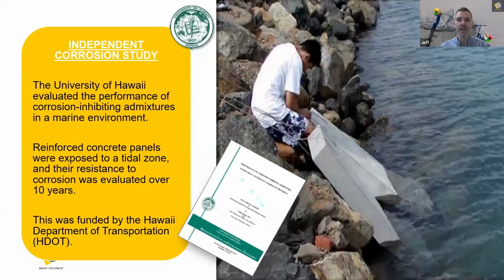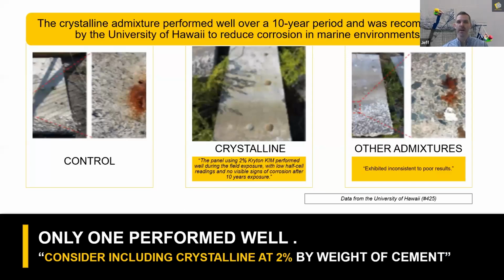Now, a really interesting study on this topic was performed by the University of Hawaii. This was a completely independent study where they exposed reinforced concrete panels in the harbor zone for 10 years. So what we're getting now is all of the critical corrosion-inducing mechanisms were acting on these panels. Not only was there high chlorides from the ocean water, but you're also getting wetting, drying, and exposure to carbonation at the same time. And these panels were treated with a variety of materials and waterproofing admixtures to assess their performance. So let's take a look at what they found.